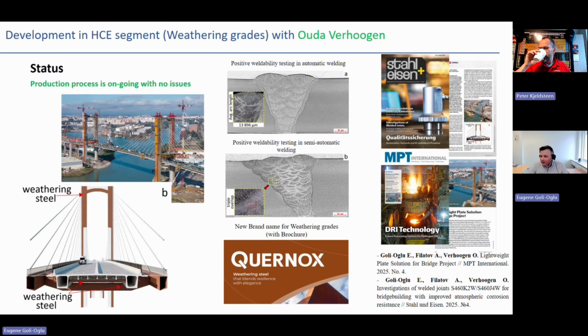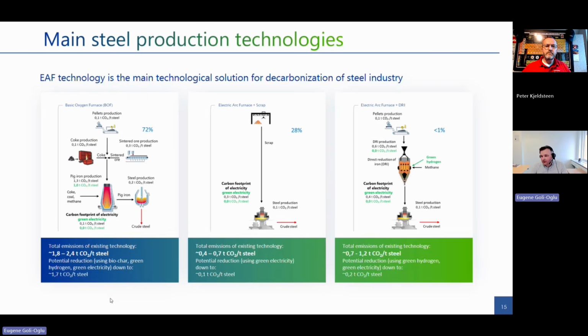emission of the steel. I made one slide, a very brief one, comparing three possible solutions here, where it's a classical BOF, and the reason why it brings higher pollution, or standard pollution, I would say, because it was a standard for many years, is because of the amount of operations plus use of fossil material like coal and coke and also natural gas. And then the typical pollution is around 1.8 to 2.4 tons CO2 per ton of steel, depending on the electricity, depending on the gas, depending on the operation and the efficiency of the process.